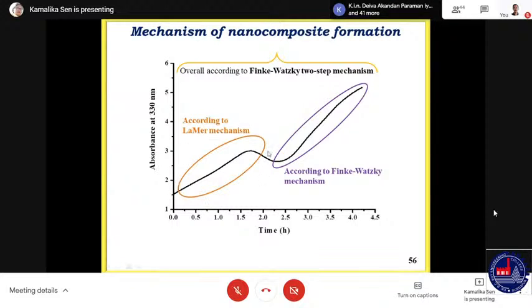First part is the LaMer mechanism, and the second part is the Finke-Watzky mechanism. How is the LaMer mechanism doing? This is characterized by the formation of nanoparticles by nucleation. First is the nucleation. This is the small particles in the solution. It is developing due to reduction of the metal, formation of nanoparticles, and that kind of nanoparticles are slowly being generated inside the solution, and then the peak falls. This is called the burst nucleation part, which means that the formed nanoparticles aggregate.